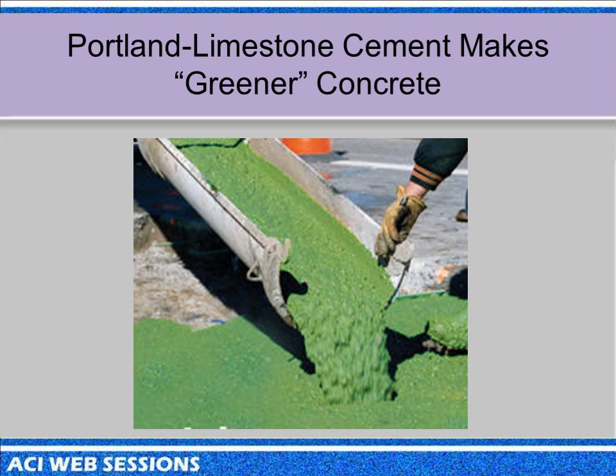Well, I didn't get into the purity issues. We have requirements on the purity of the limestone and on contaminants, mainly organics and clay components in the limestone. We meet the same requirements as the European specs for limestone. So if the fillers met the same requirements and they could be dispersed in the mix at similar replacement levels, you'd probably have pretty similar performance.